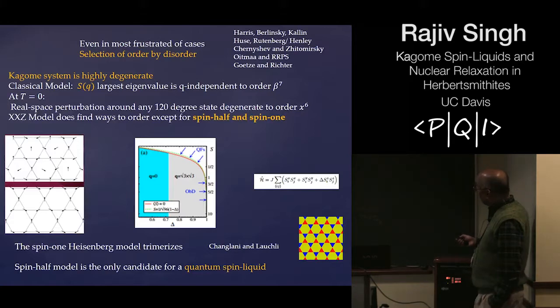A few different ways of studying this model, for example, is to study the structure factor, say for the classical model in a high temperature expansion. What one would find is that it remains independent of Q up to order beta to the power 7, but then at a higher order there is a selection, there is some Q value at which the structure factor starts to grow, and essentially at the end the model ends up ordering. So similarly, if we go to 0 temperature, yes.